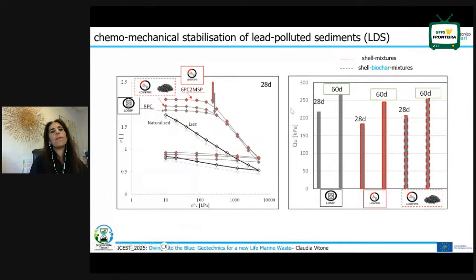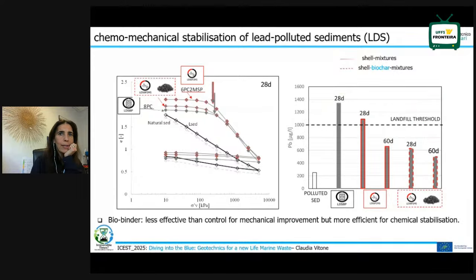In terms of unconfined compression strength, you can observe here that the control mixture for the lead polluted sediment is performing a bit better than the one with the shells. But we have an increase of strength for longer curing time. So we should wait more than 60 days to see how the story is ending.